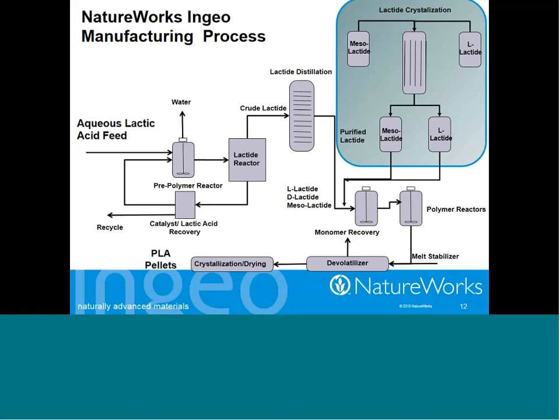In this instance, I guess I'll mention that in the crystallization process, we are able to enrich the stereoisomer content, or the enantiomeric excess, of the L-lactide, so it is possible to remove D-lactide from an L-lactide stream via crystallization, because the L-lactide basically acts as the chiral resolution agent in the crystal nucleation process to give us a crystal that's enriched in L-lactide and a supernatant that's enriched in D-lactide. So that's a phenomenon that works in a general sense when you have a stereoisomer population that's better than 90% to start with in the first place.